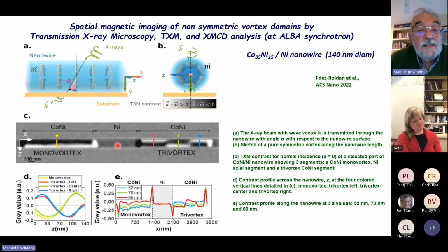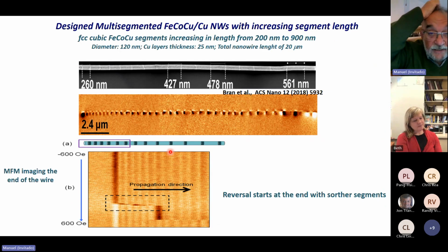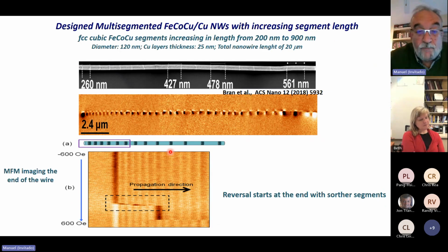We have an axial domain in the nickel, and we have a three-vortex structure in the segment to the right. And finally, the multi-segmented nanowires with designed length of the magnetic segment. So here we have iron, cobalt, copper. With copper, you see the copper is the white contrast here.